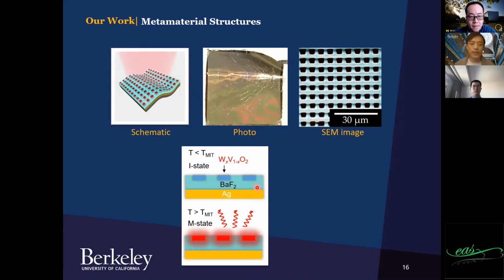It has 3 layers. The top layer is tungsten-doped VO2, and it was patterned by lithography. And this is a barium fluoride dielectric spacer, and this is a silver metal back mirror. When the temperature is below the phase change temperature, the tungsten-doped VO2 is in its insulating phase. It's a transparent material. So the whole structure serves as a mirror, and it has a low thermal emittance. And when the temperature is increased, the tungsten-doped VO2 becomes a metal, so that the whole structure turns into a classical super absorber metamaterial pattern with a high thermal emittance.